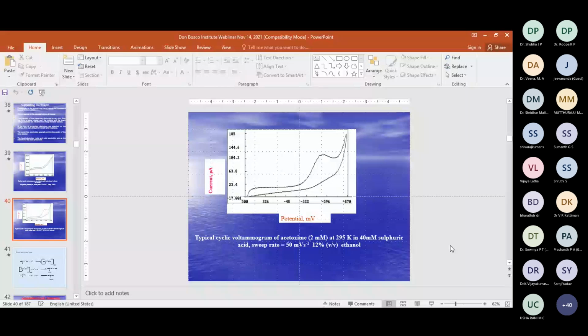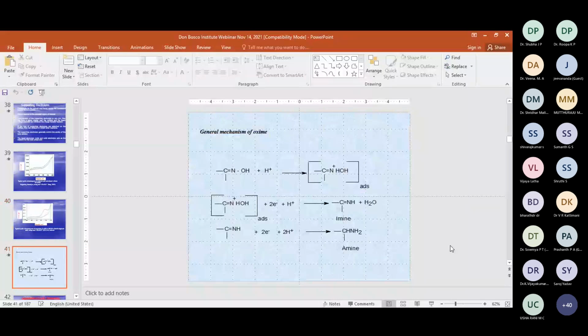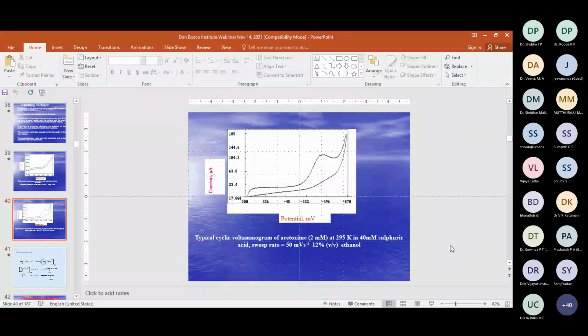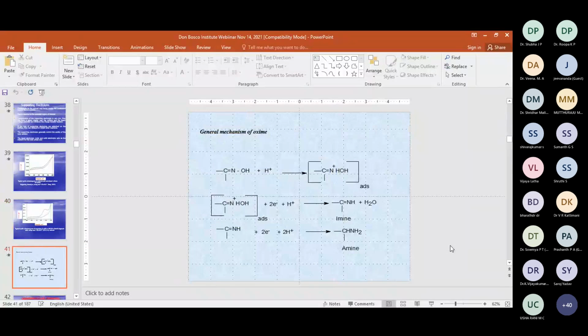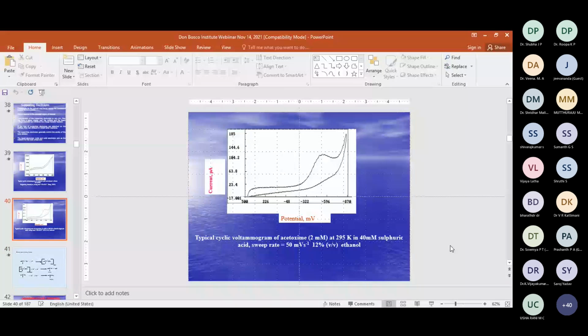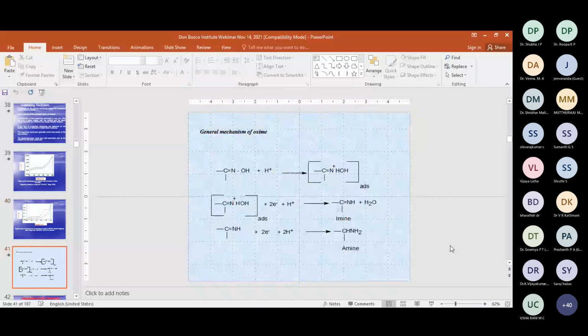How to check? In organic chemistry, many people are working especially on the conversion by reduction from oxime molecule to amine molecule. By using cyclic voltammetry, you can reduce oxime to amine molecule. So you got only one reduction peak. That means you can say whatever oxime molecule you have taken is completely reduced into the amine product. If you get a reduction peak as well as an oxidation peak, you can say you got imine from the oxime. But if you got only one reduction peak, you can say you got the amine molecule from the oxime molecule.